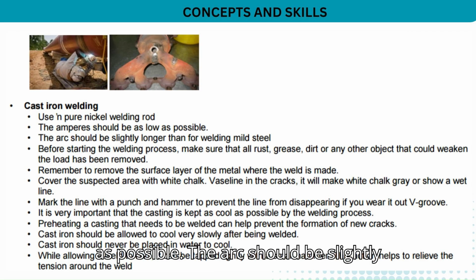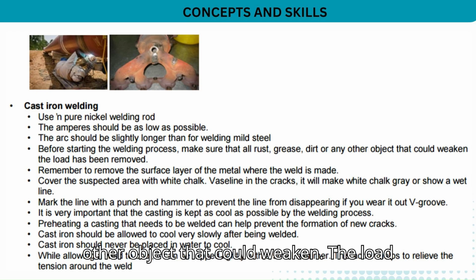Cast iron welding. Use a pure nickel welding rod. The amperes should be as low as possible. The arc should be slightly longer than for welding mild steel. Before starting the welding process, make sure that all rust, grease, dirt or any other object that could weaken the load has been removed. Remember to remove the surface layer of the metal where the weld is made.